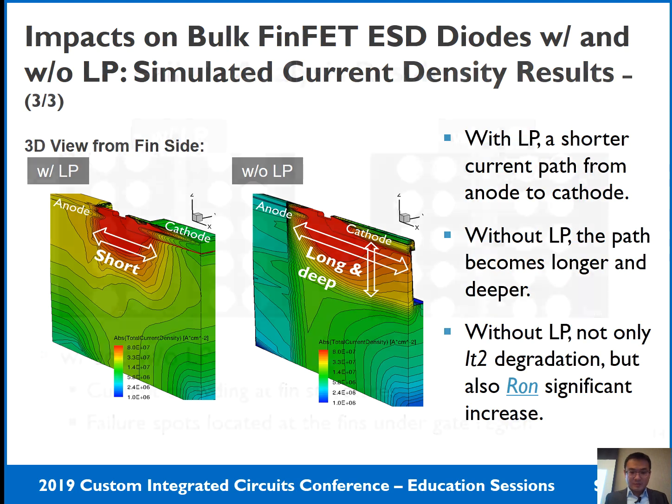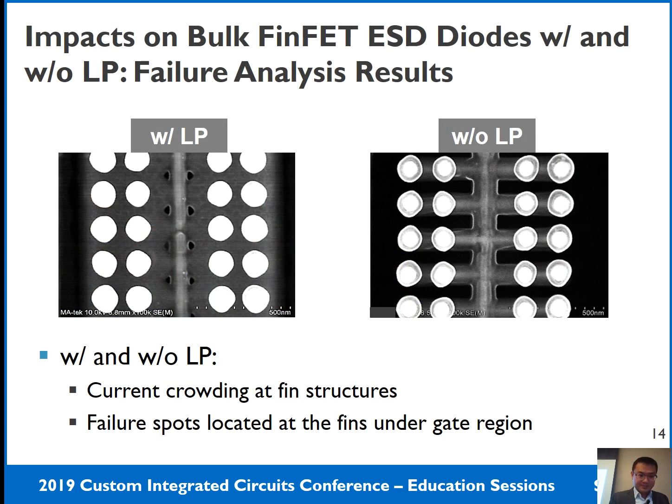The next thing, the failure analysis result indicates that no matter with or without the landing pad, the failure spot is always located at the fin structure just under the gate region.